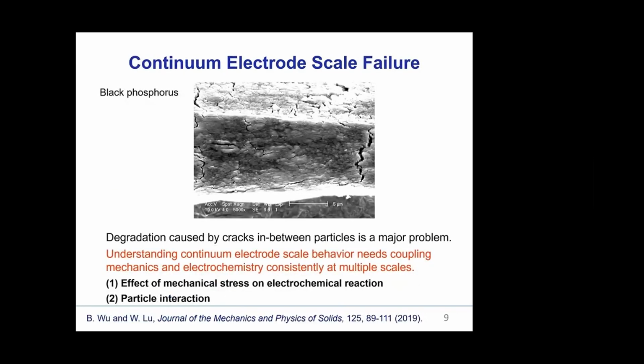However, experimental observations show that electrode level crack and fracture can occur and have a major impact, especially for high energy materials. For instance, black phosphorus is a promising anode material with a high energy density. We can observe significant electrode level cracks in the electrode.